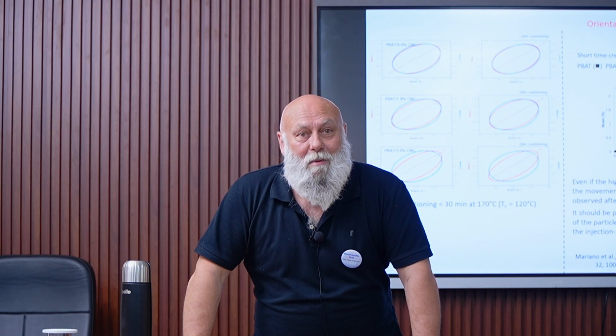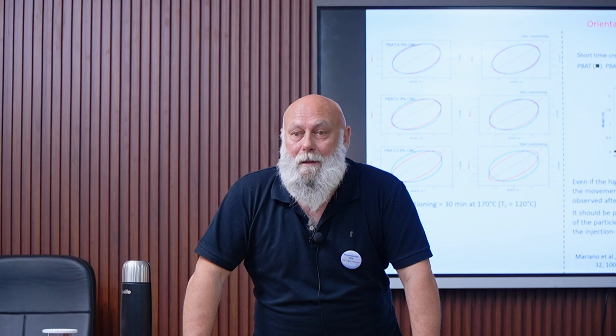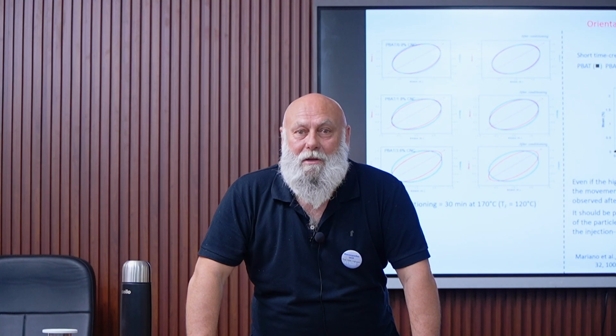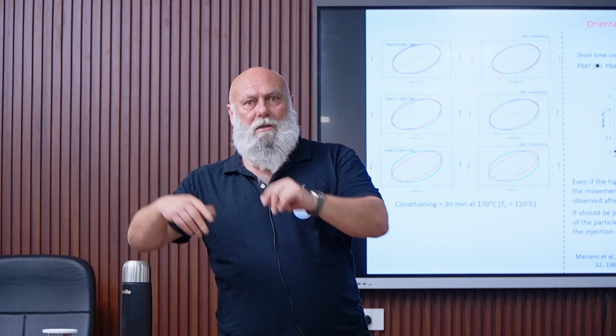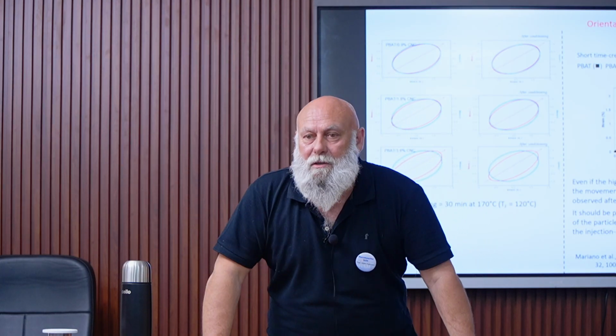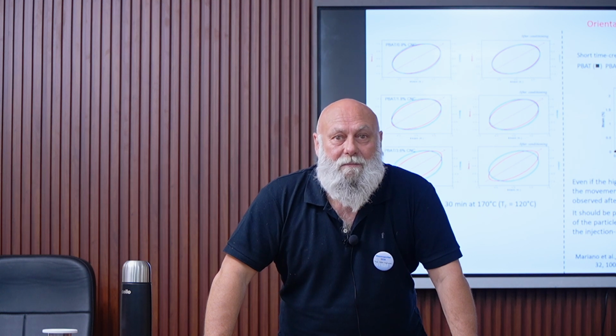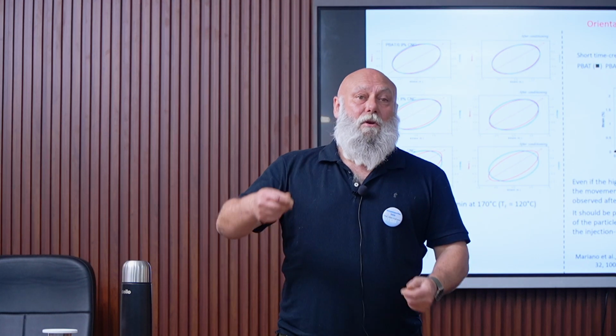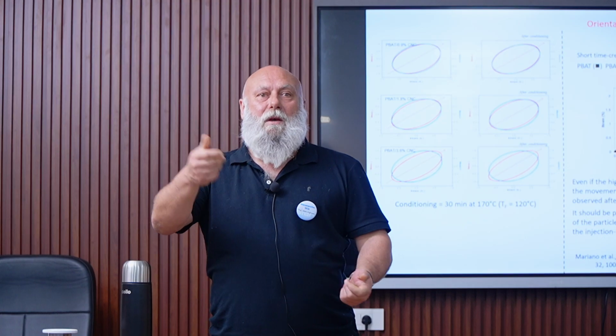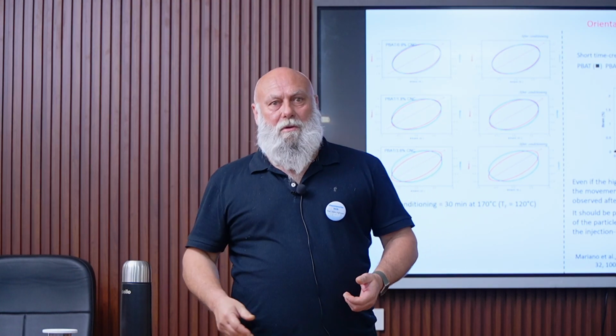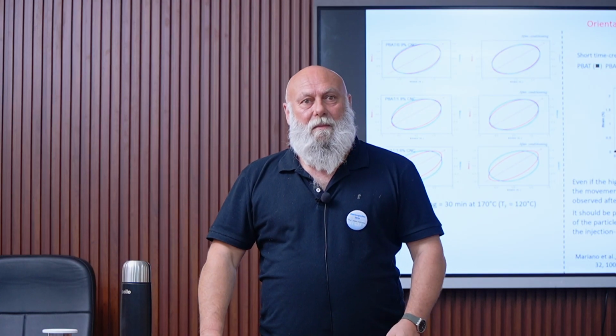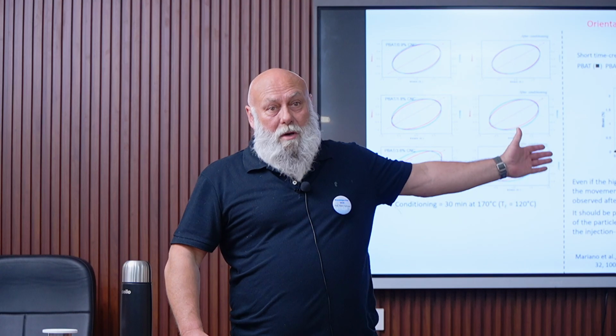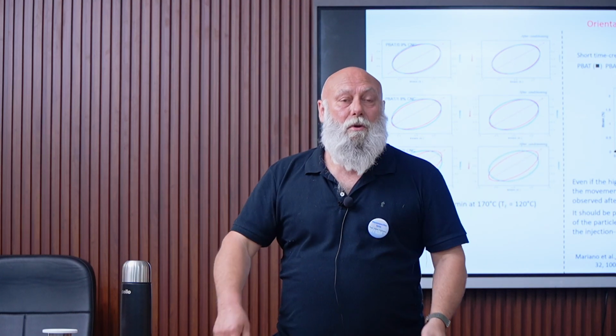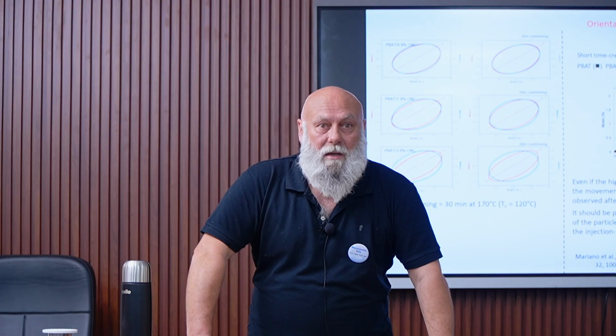So what is the mechanical parameter which is constant? I pose the question to all of you. Which mechanical parameter is constant during a tensile test? Tensile strength. No, in fact, the elongation rate: you extend at 10 millimeters per minute, for example. This is a parameter which is constant. And so in a creep test, the stress applied to the material is constant.